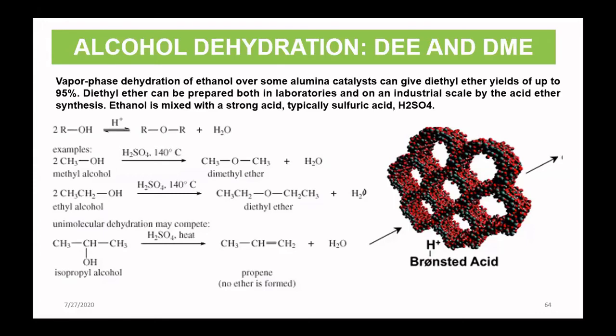We dehydrate the alcohols, for example, using an acid catalyst, solid acid or homogeneous, and then we obtain the diethyl ether or the dimethyl ether, depending on the reagent that we use. If we use methyl alcohol, we obtain dimethyl ether, and if we use ethyl alcohol, we obtain diethyl ether. The temperature is high, around 140.